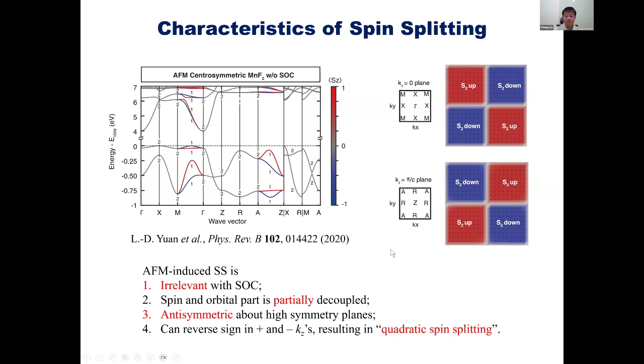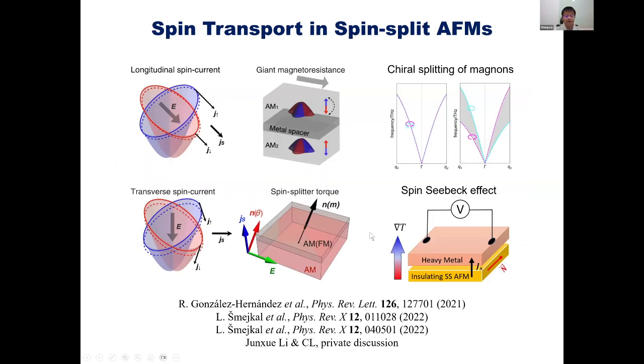terms in k. As to the potential applications, for example, in these papers by Dr. Šmejkal and collaborators, we see that altermagnets can produce spin currents that are perpendicular to the charge current, convenient for spintronic devices. Also, heterostructures made by altermagnets can realize giant magnetoresistance and spin splitter torque. The splitting of spin also leads to the chiral splitting of magnons, as just mentioned by Dr. Šmejkal as well, which can be probed by, for example, the spin Seebeck effect.